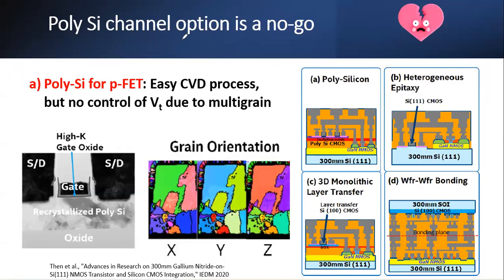The polysilicon channel is one of them. On the right-hand side there are 4 figures, 4 options you could do. With polysilicon, you don't need to do a layer transfer. I'm sorry, this is an isolation. You put an oxide after you build your N, and then you deposit silicon on top. That's the best case. You don't need to do a layer transfer. You don't need to put SOI. You just put an oxide on top, and then you layer a silicon channel on top.